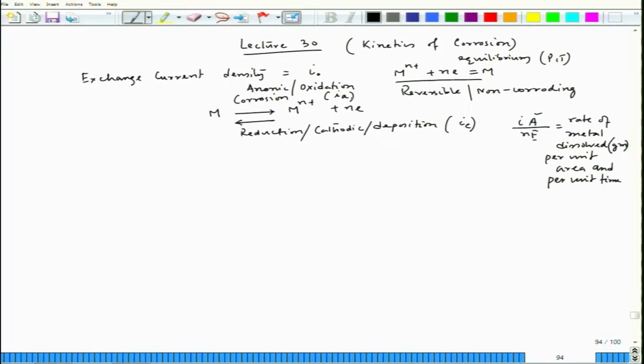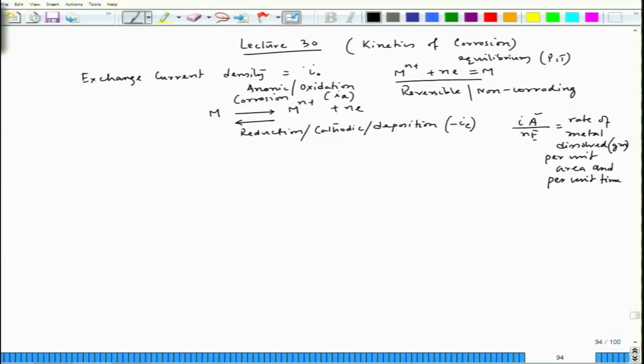And in order to indicate the direction of flow of these two currents, we have put a negative sign in front of IC. This negative sign does not indicate that the value of current density is negative, it indicates that it flows opposite to the anodic current or the corrosion current density. Now, when they reach equilibrium, we come across I0, the exchange current density, which is basically the reversible condition and non-corroding situation, because whatever metal ion forms, that metal ion goes and deposits on the metal surface.